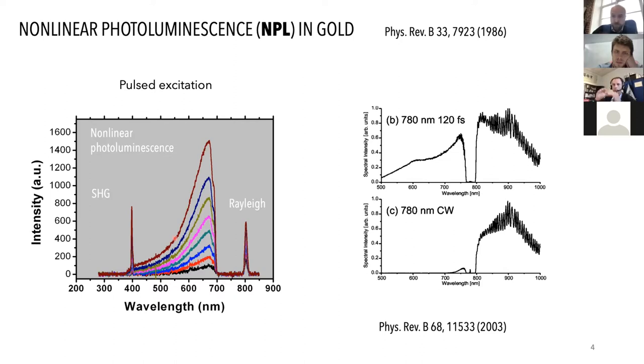They are, of course, respective weight is a little bit different, but usually when we have a strong PL response, we also have a strong second harmonic response. But they follow different selection rules, but they are both sensitive to the local electric field. So when the local electric field is high, both of these signals are basically boosting up.